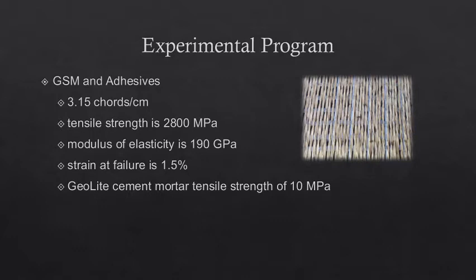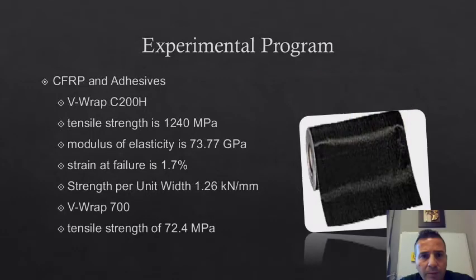The tensile strength of this steel without the mortar is 2800 megapascal. The density of the sheet is 3.15 cords per centimeter. The modulus of elasticity is 190 gigapascal, and the strain at failure is 1.5%. And this is the geolite cement mortar that is used. Again, it has a tensile strength of 10 megapascal. These are the U-wrap sheets that we use at the ends, and they were bonded.